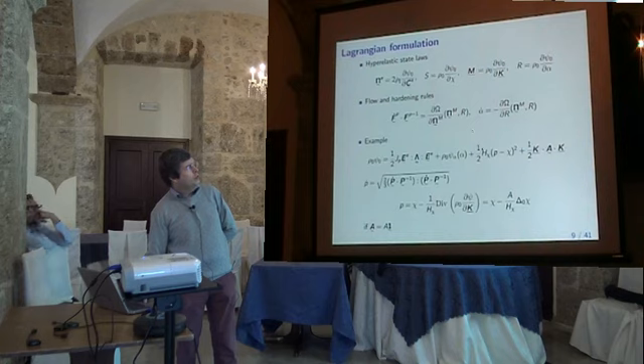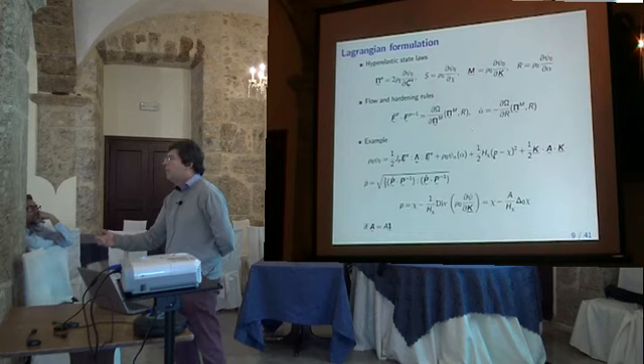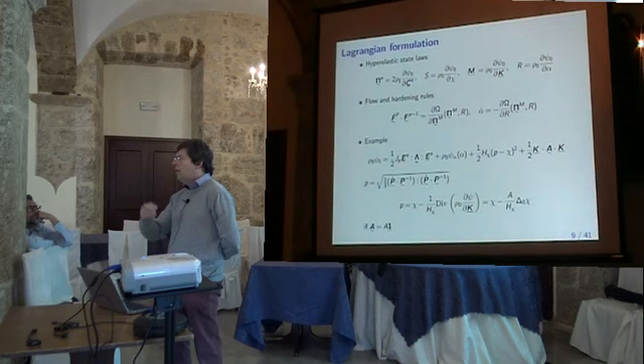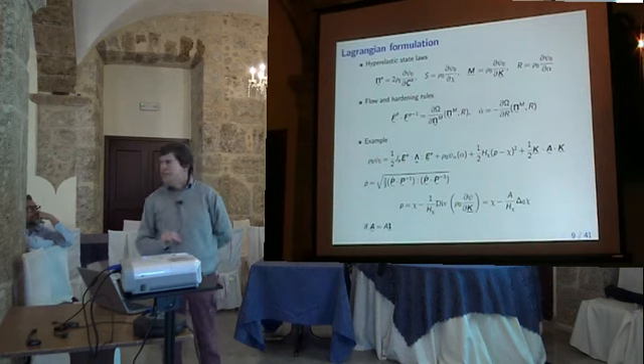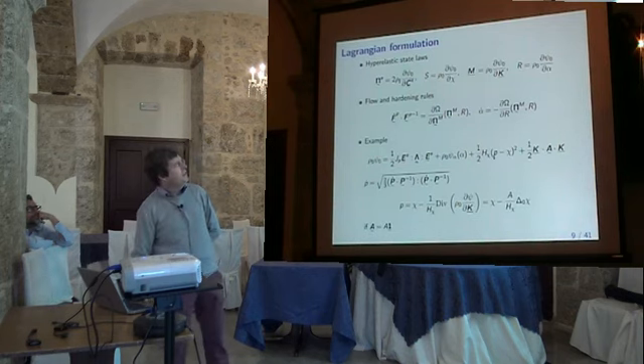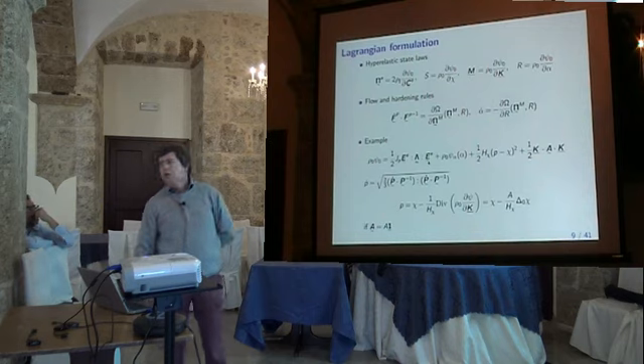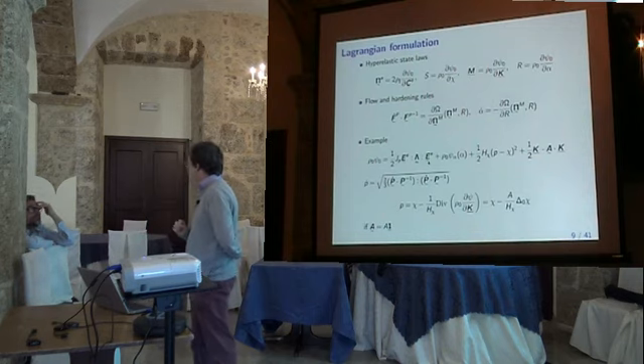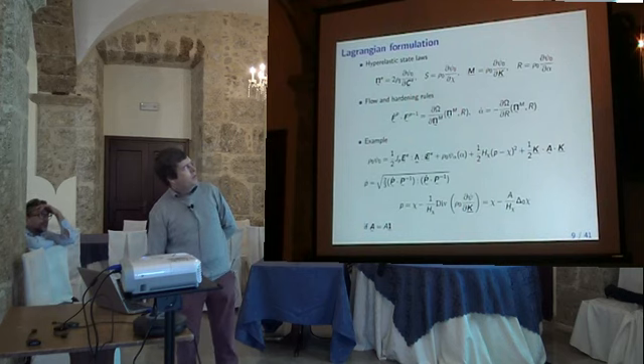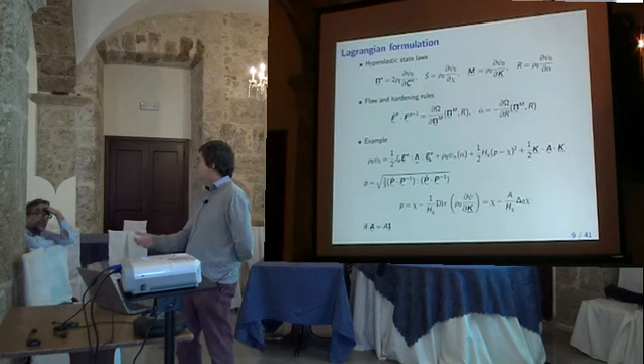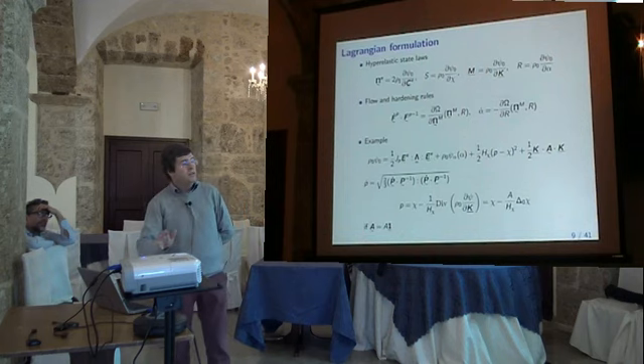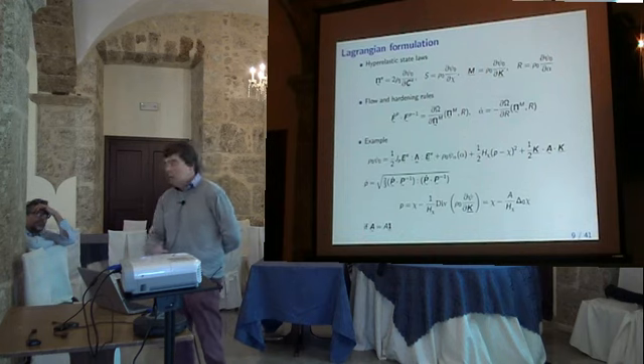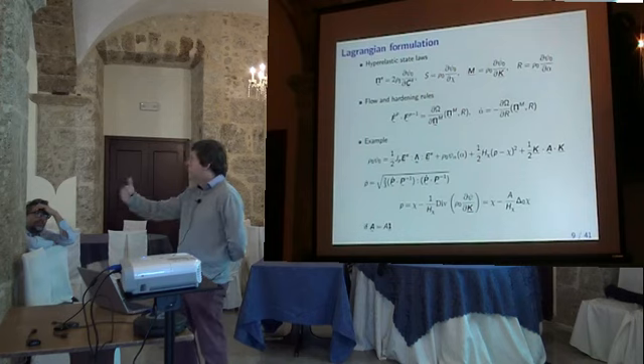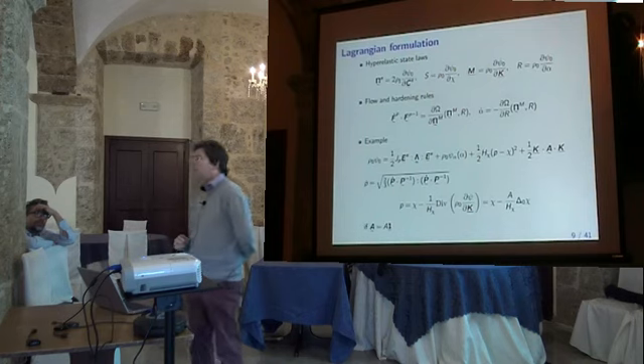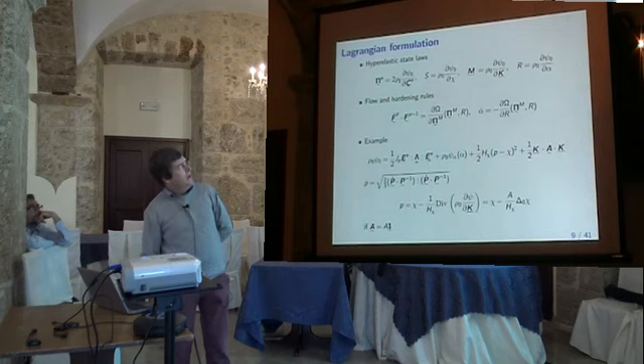And now I come to the point. I propose a very simple example of constitutive law. I take first the choice of the free energy function. So let's take a very simple case. I am interested in metals, so a quadratic potential will be enough for me, with respect to the Green-Lagrange elastic strain. It's not very sophisticated, but it's enough because the elastic strain remains small. So even if the model is not so good, I mean, regarding convexity condition and all this, but this is enough. This I will discuss later, the hardening.